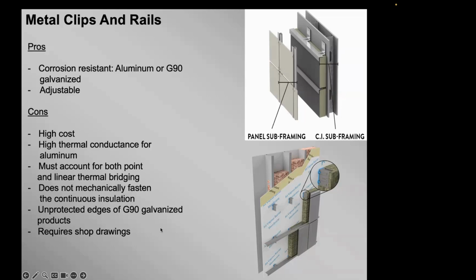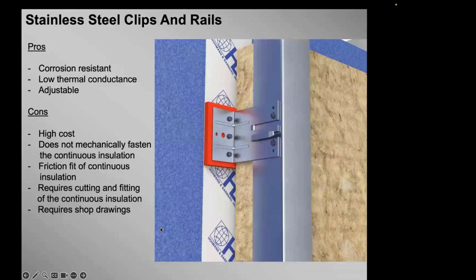And this system does require shop drawings. So I'm seeing more and more of these come out with the stainless steel clip and rail. It's very corrosion resistant. It's low thermal conductance. Stainless is a lot lower conductance value than cold roll steel and much, much lower than aluminum. And it is adjustable. They're starting to build adjustability into it, but it's a high cost. There's a big piece of metal here, and the stainless is very costly.